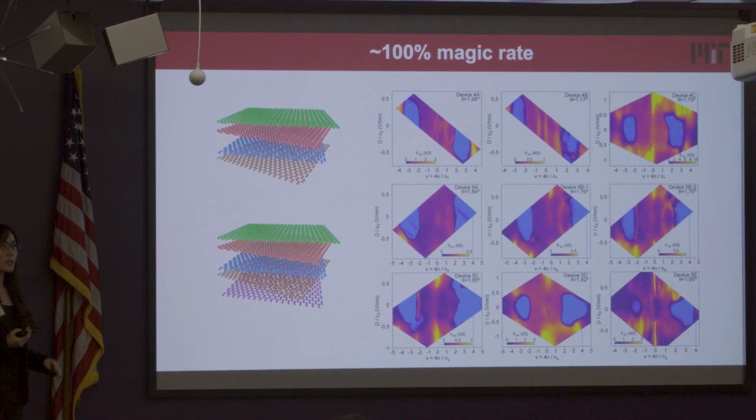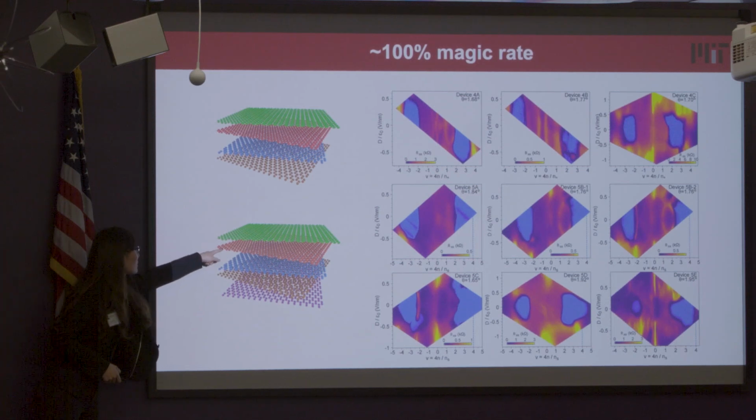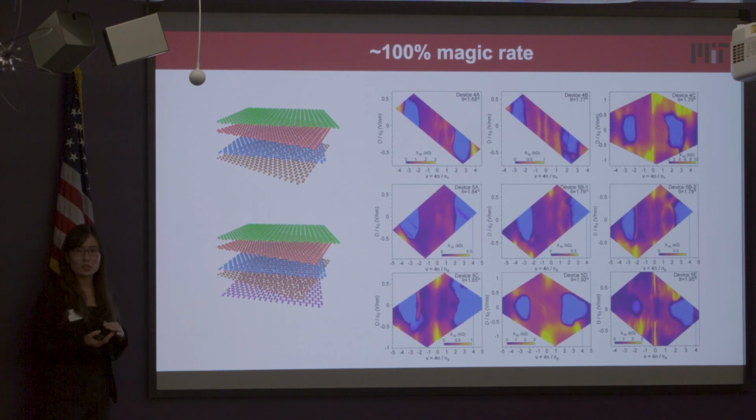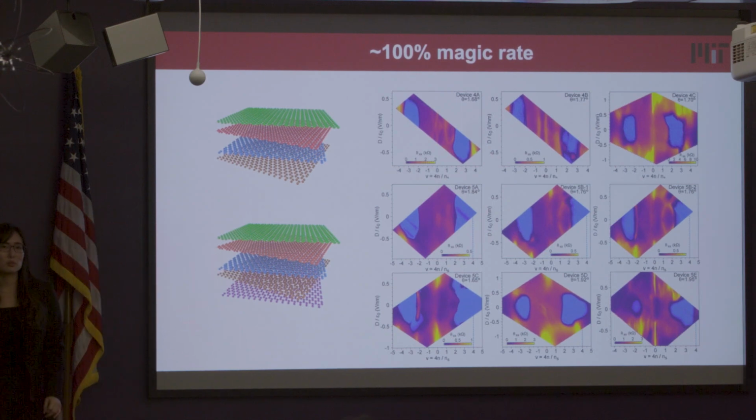Yeah, the gating is actually not through directly putting a voltage on your system. It's more like you have separate metallic gates. We keep our system at 0 DC voltage and use AC to measure the resistance. We could of course also apply some gate to the middle structure, but I'm not sure you can separately gate that layer differently from the others, because they're all in some sense shorted. They're all graphene, they're conducting. So I think there is a little bit of technical difficulty.